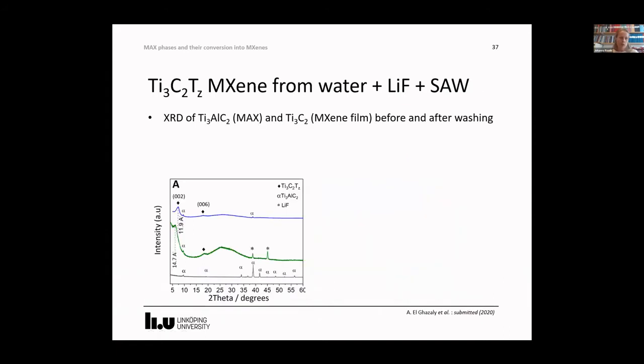If we turn to our experimental data, you see here XRD of the MAX phase at the bottom, and XRD of a freestanding filtered MXene film obtained from this new method. The residual amount of lithium fluoride here can be removed by washing, then you get this XRD, but since we want to reduce the synthesis time and the number of steps, we focus on this one.